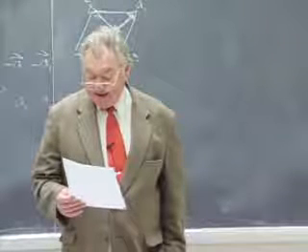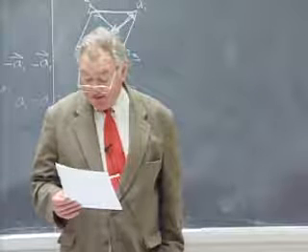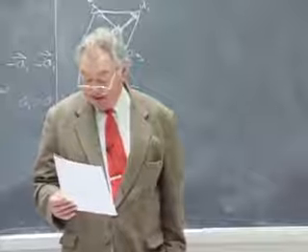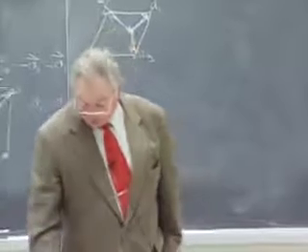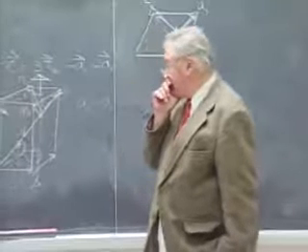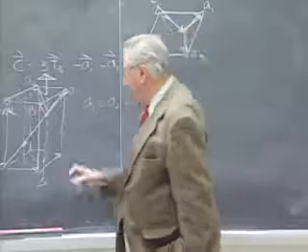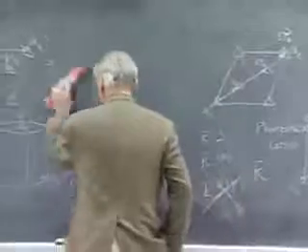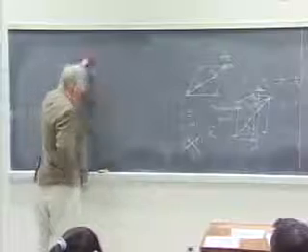P6 has a six-fold axis at the origin lattice point. The two centers of the triangles are three-fold axes. So primitive for the six-fold axis, either P6 or P6mm, is the only choice. So if anybody's counting, and I wasn't, we've got 11 lattices so far.